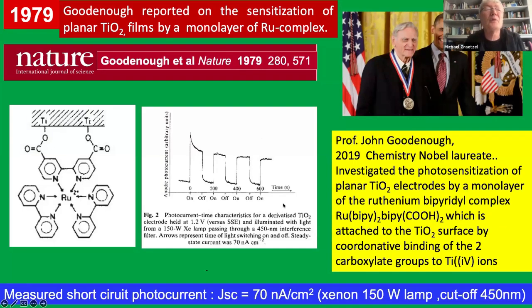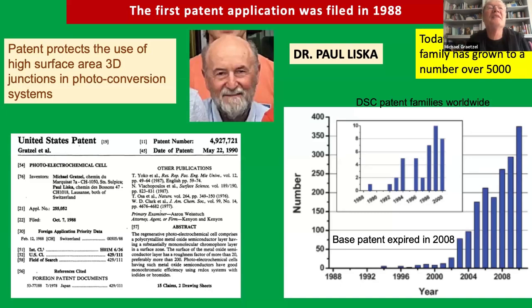However, we had a different approach. We had been working on colloidal semiconductors, the first actually to investigate those colloidal semiconductors. And we had found that we could sensitize those colloidal particles very efficiently. Injection rates were much faster than recombination rates of carriers. And so we took a patent out in 1988, after we had done some model studies on high surface area electrodes. And so that patent was the base for the DSC development.